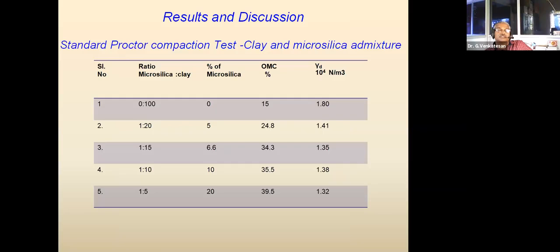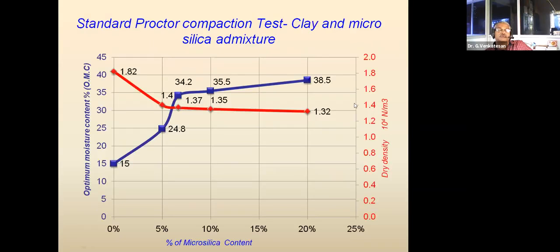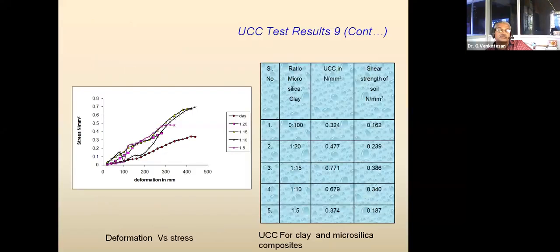Now the results and discussion. According to the 5 ratios, with the percentage of microsilica up to 20%, we found the OMC value and the gamma d value. Based on the interpretation, on adding microsilica, the optimum moisture content value is increasing. The dry density value is decreasing because of adding microsilica to the clay soil. The density varied; a decreasing scenario of gamma d was observed.